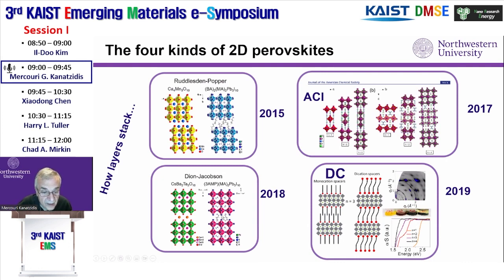And so we made perovskites where actually they have this stacking as well. So these are the DJ perovskites. We have also seen perovskites with very small cations, where we have one cation in the cage, and then the small cations alternate order between the cages. And the interest here is in stacking, in one direction, you see the stacking is shifted by 1/2, just like Ruddlesden-Popper. But if you turn it 90 degrees and look at it again, the stacking is eclipsed, not shifted. That's more like Dion-Jacobson. So that's an interesting one here as well.